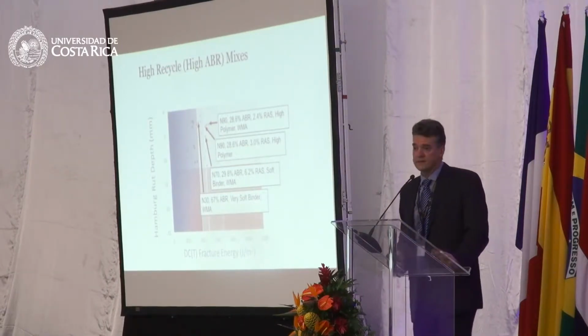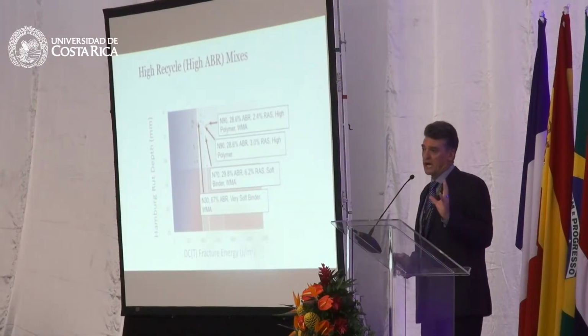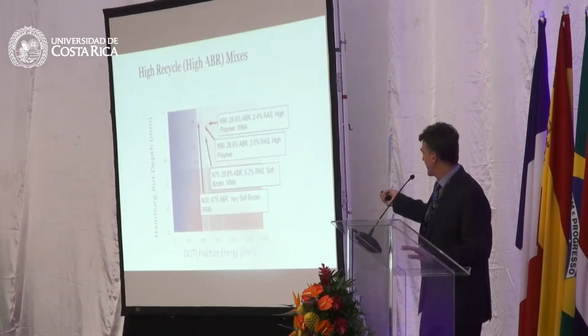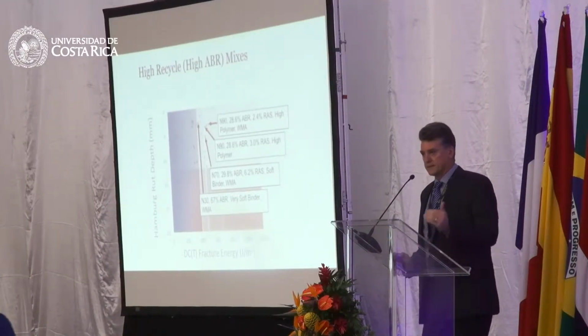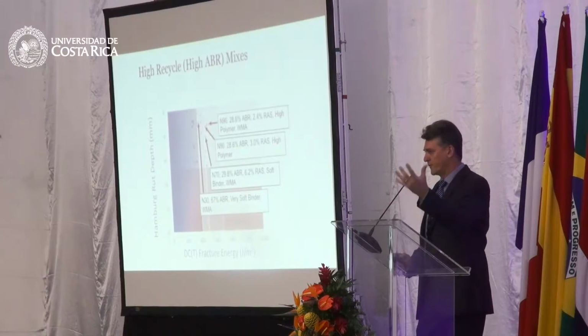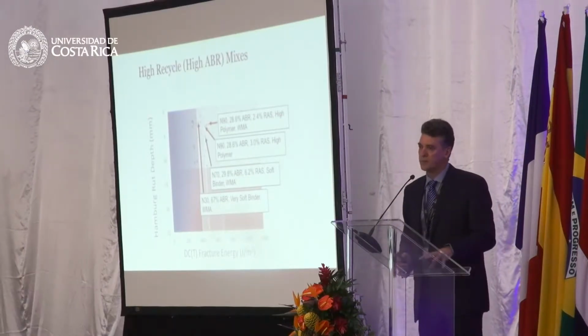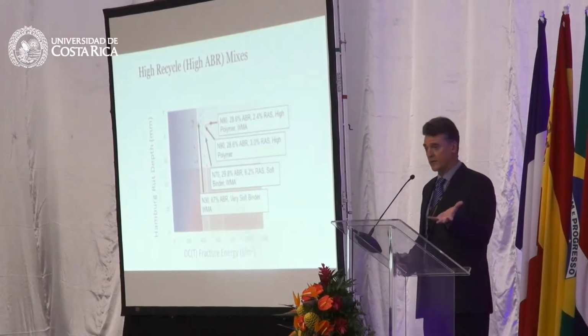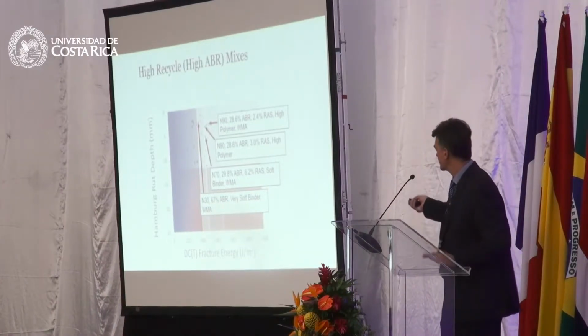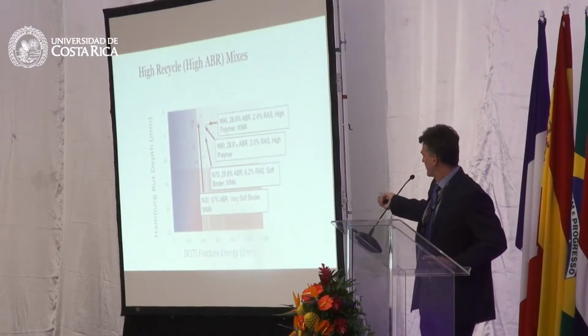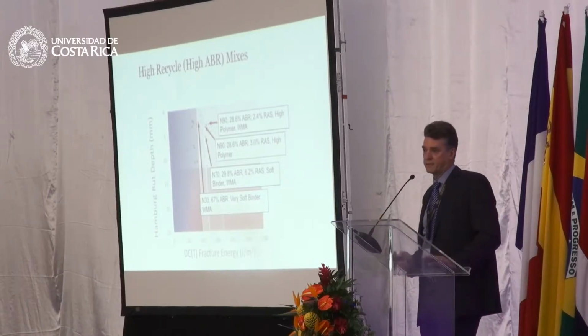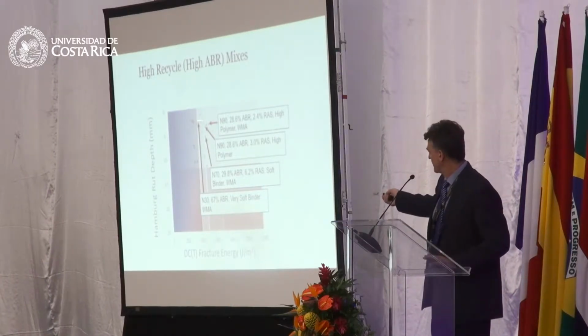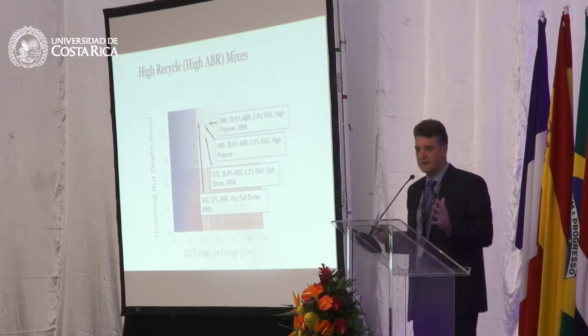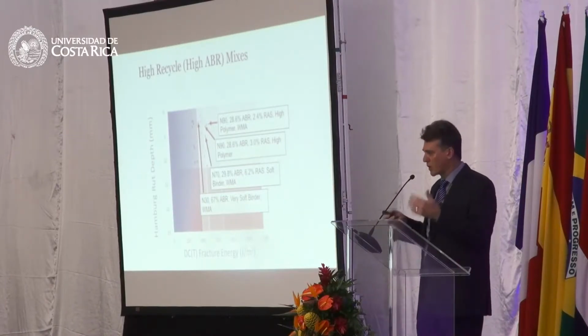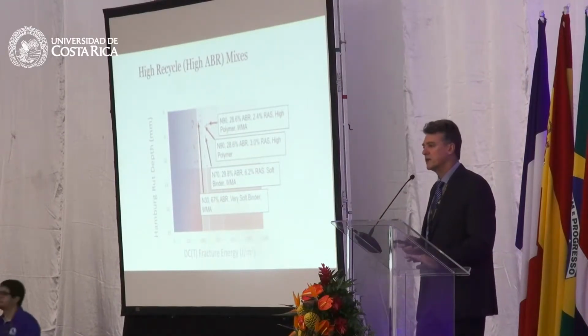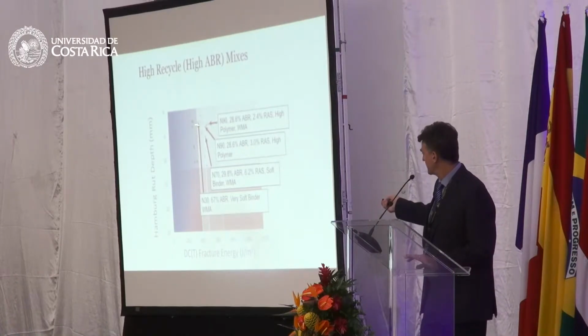We can also design very high recycled content mixtures. I call this asphalt binder replacement—you're replacing what would have been new virgin binder with recycled binder, either from recycled asphalt concrete or maybe roofing shingles. We can replace anywhere from 30 up to 67% binder and still be in some of these passing zones. They may be more suitable for low volume roads where you can tolerate a little bit of cracking for an economical, sustainable design.